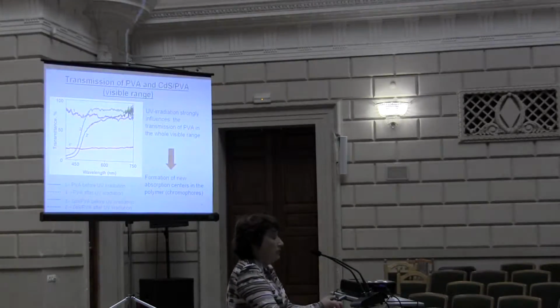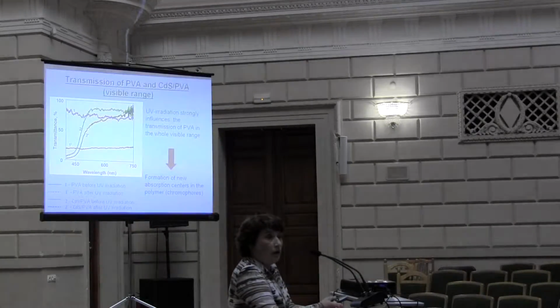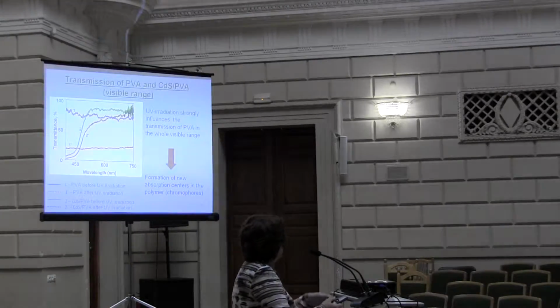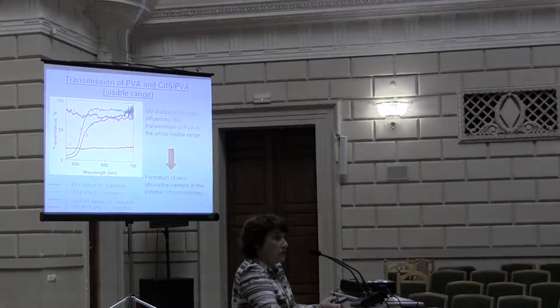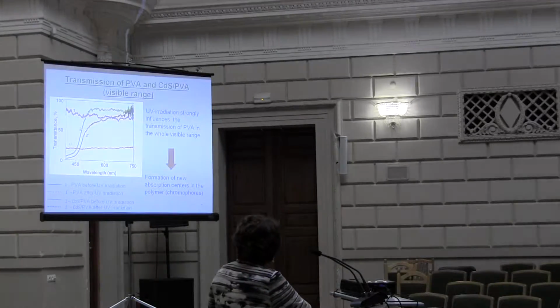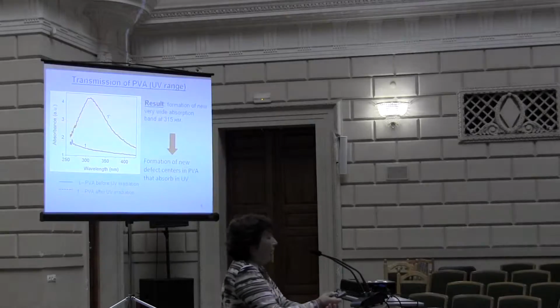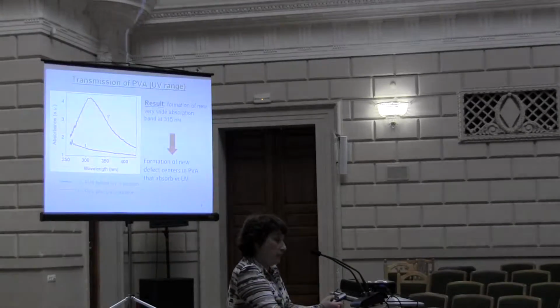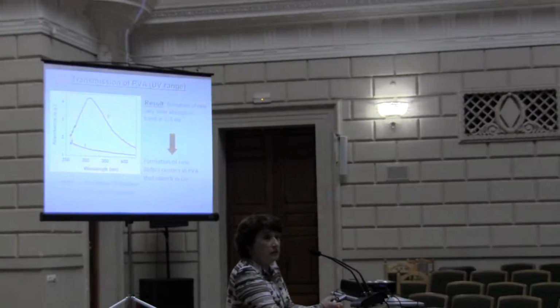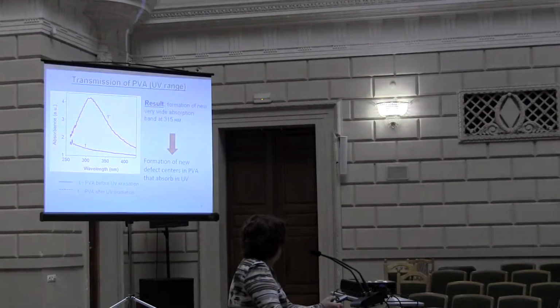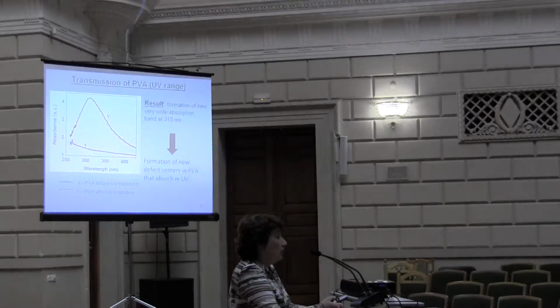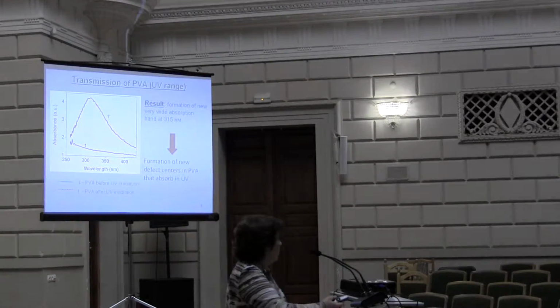What about the composite? 2 and 2 prime are the transparency spectra of our pure polymer and nanocomposite. You can see that there is some background, but the changes are much smaller. And what we did not see by the naked eye is the influence in the UV region. Here is the plot of the absorption in the UV region.